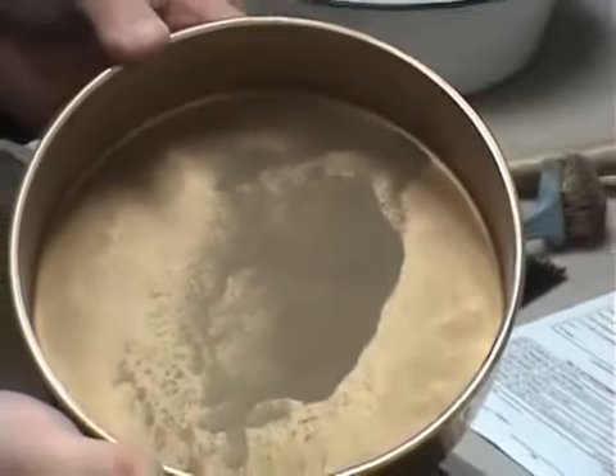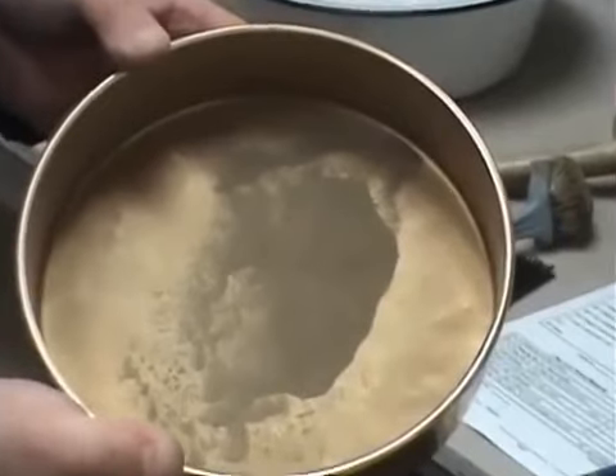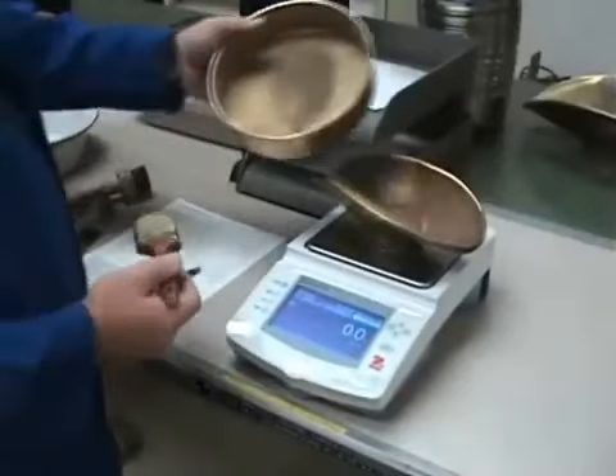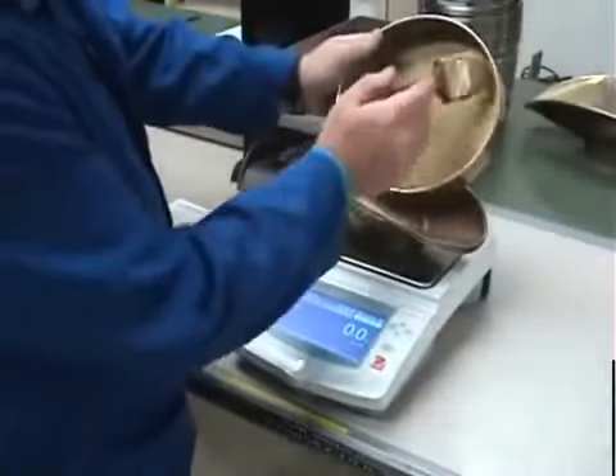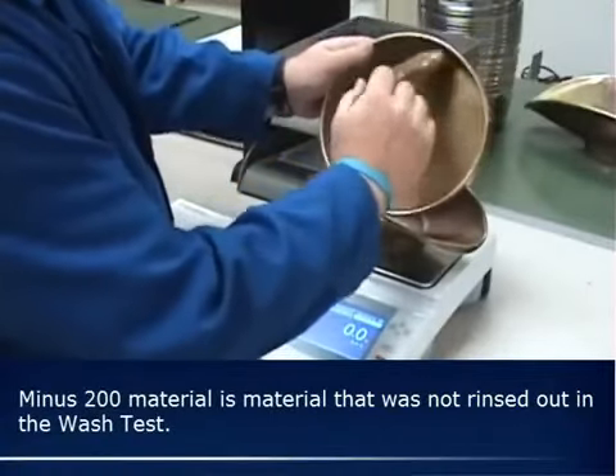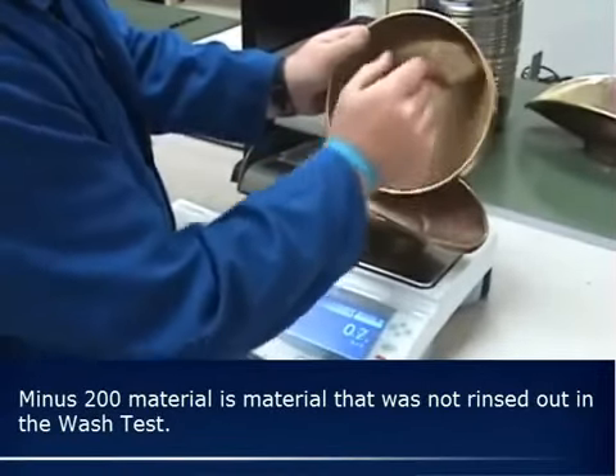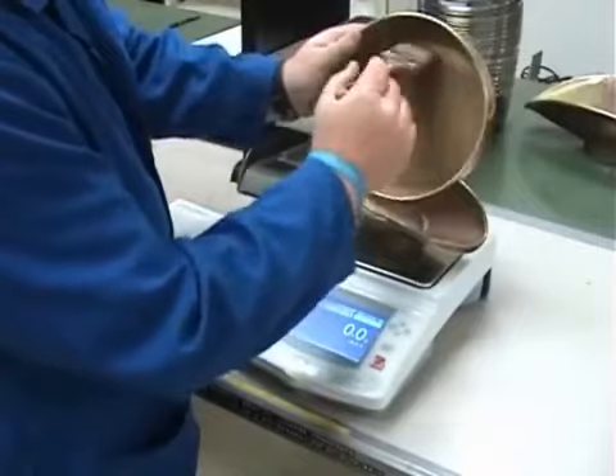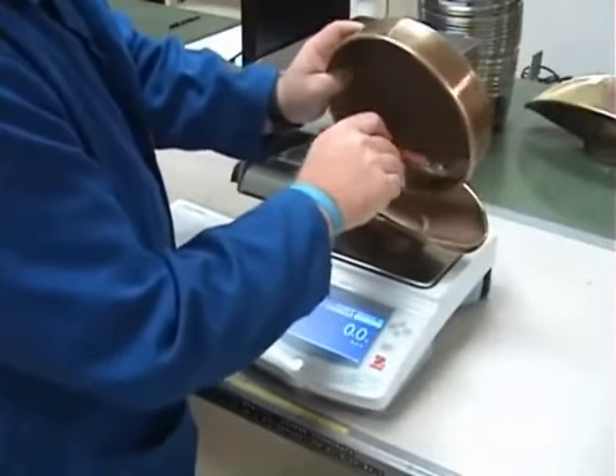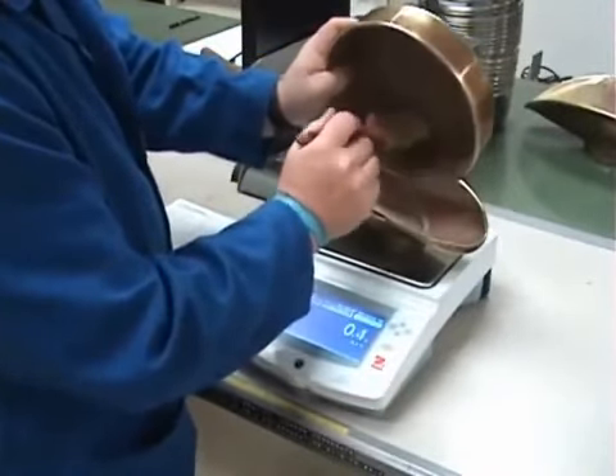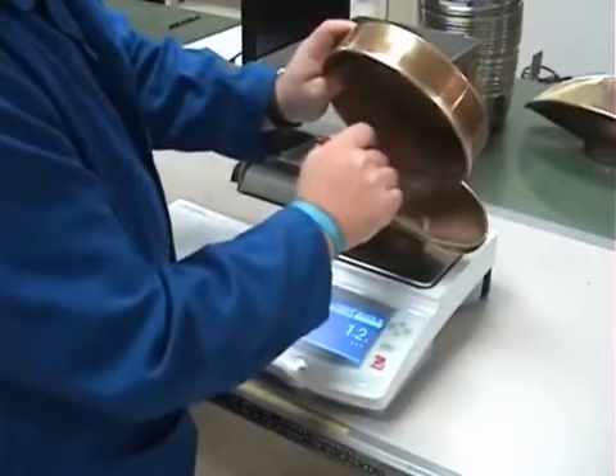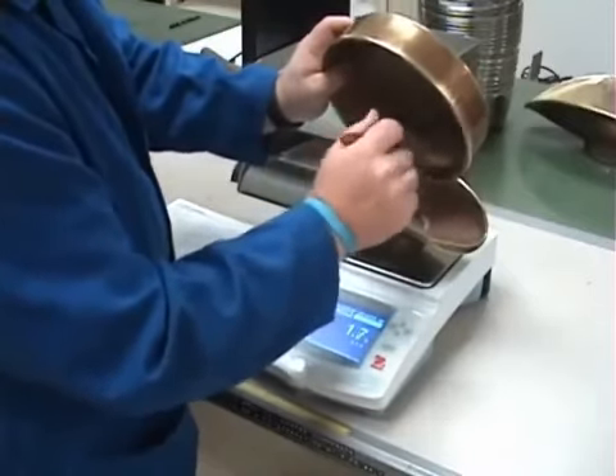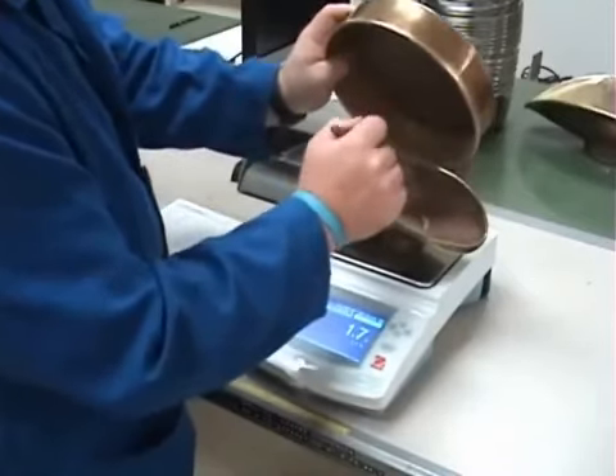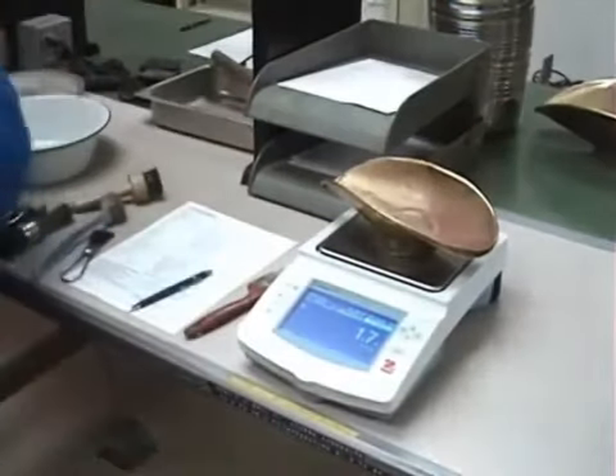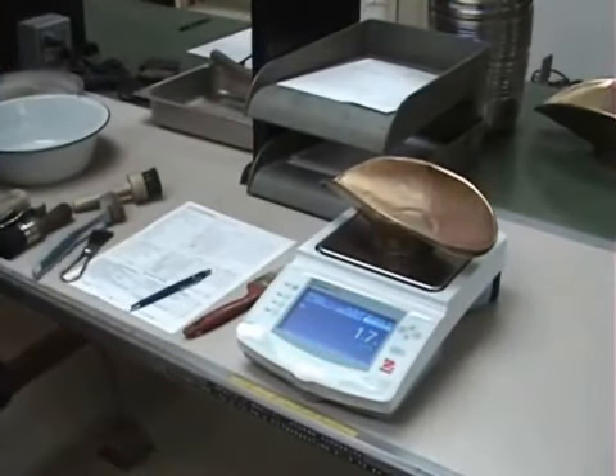The material in the bottom of the nest of sieves is minus 200 material. This material is weighed and recorded. The minus 200 percentage is derived from both the wash and sieve analysis tests. Weigh and record this weight. In this case, it's 1.7 grams.